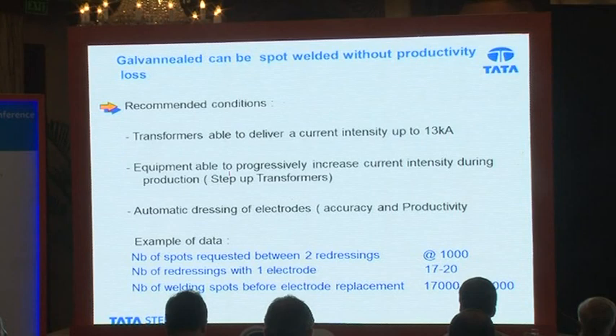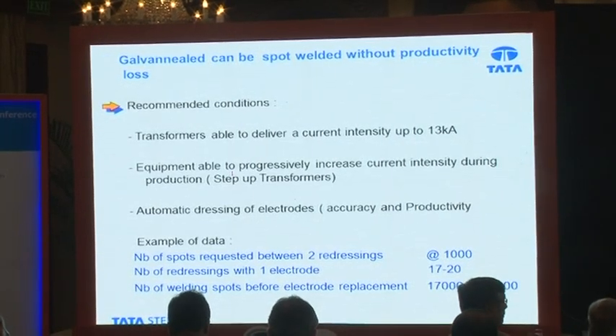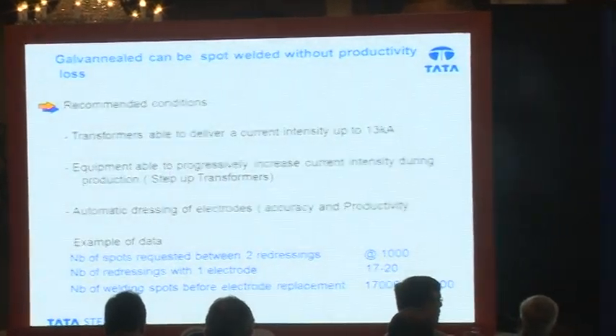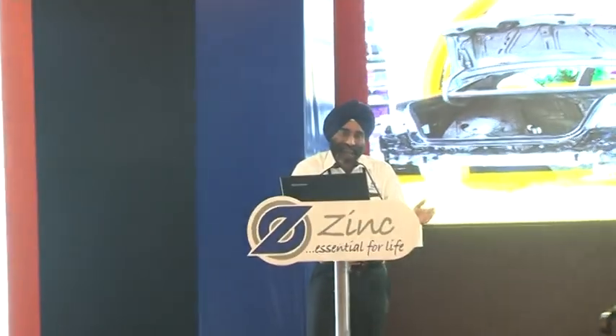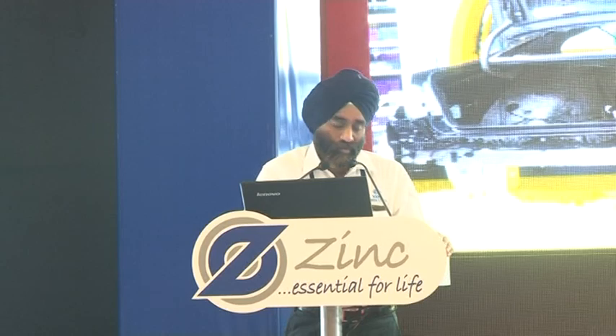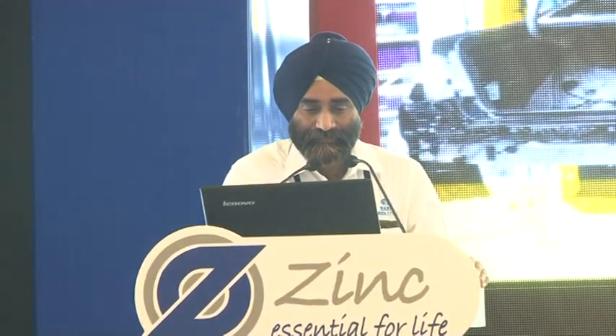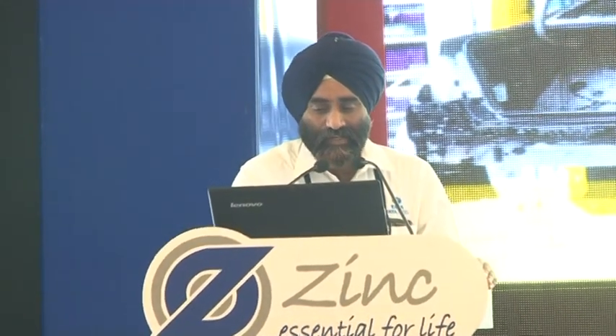The automatic dressing of electrodes. These are some of the recommendations which the automaker has to use, and then they can easily transit from uncoated steel onto galvannealed steels. This I already talked about, that we recommend a tricationic phosphate with fluorine addition, and this is done at the phosphatation bath so that they get the 12-year perforation corrosion warranty.